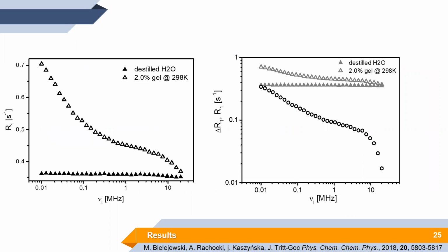And now, let us take a closer look at the NMRD profile of the ionogel. Not for the ionogel, but for the hydrogel first. We can see a very strong dependence in the only 2% gel phase at room temperature. So the open triangles are in the gel phase, the solid triangles are for the pure water. Because the NMRD profile for the pure liquid is almost like a constant in the whole frequency range, and we are especially interested in the low frequency range, we did a small mathematical trick, just to make the situation simpler for analysis. We actually subtract from the NMRD profile of the gel the NMRD profile of the liquid.